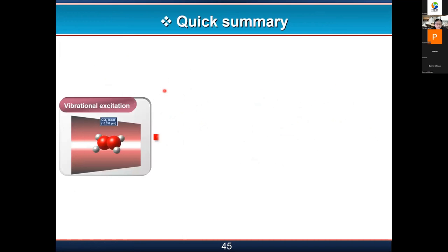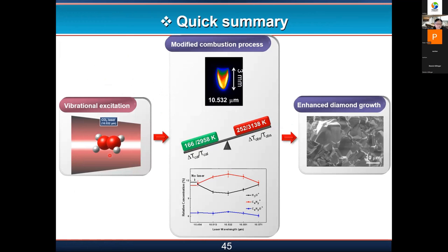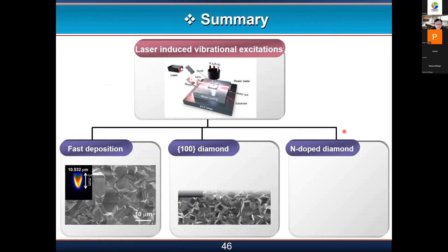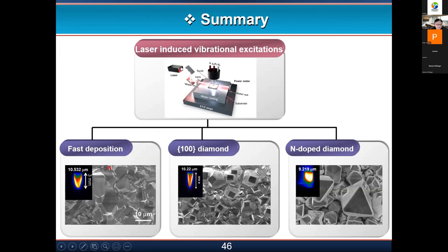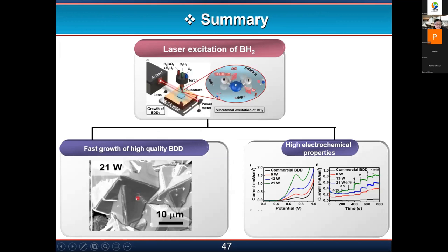Okay, just a quick summary: we can use laser excitation to resonate the vibration modes of precursors, to enhance diamond growth and improve the crystallinity. At the same time, we can also achieve a higher deposition rate and better crystallinity. And one topic I didn't mention is that we can control the growth orientation of diamond. We can use this method to control whether we get a 1-0-0 surface or other surfaces, to get boron doped diamond with a high doping rate and high crystallinity.